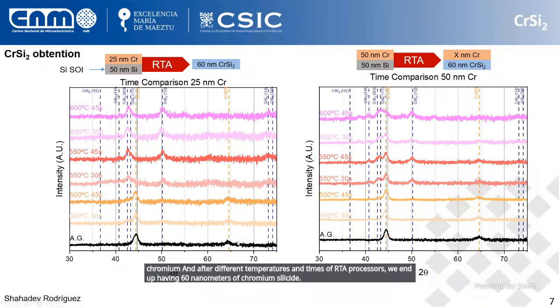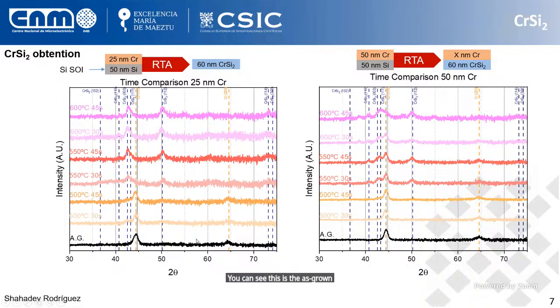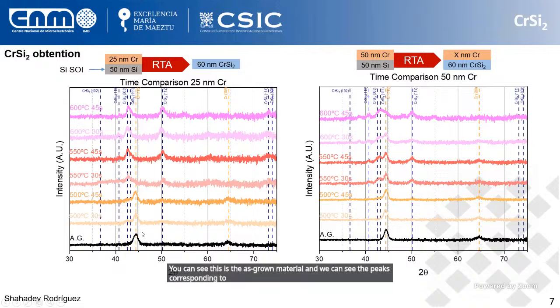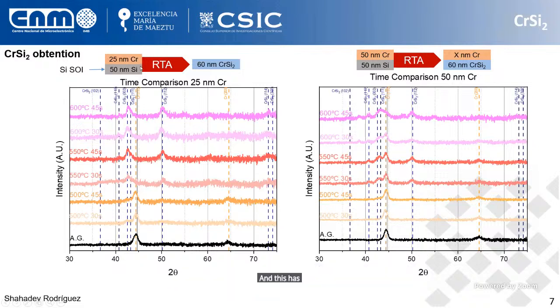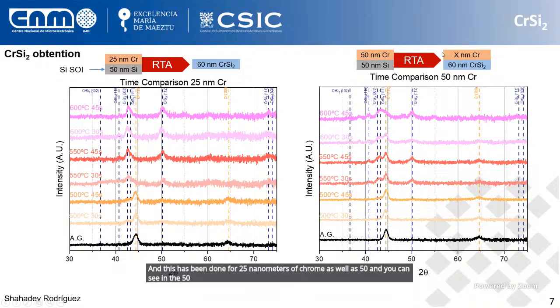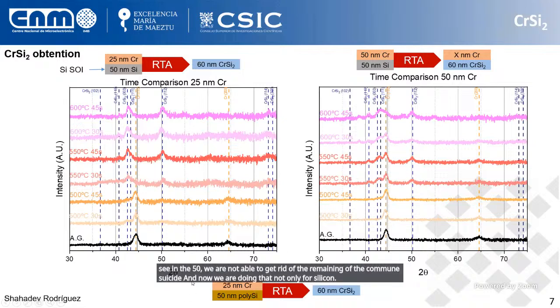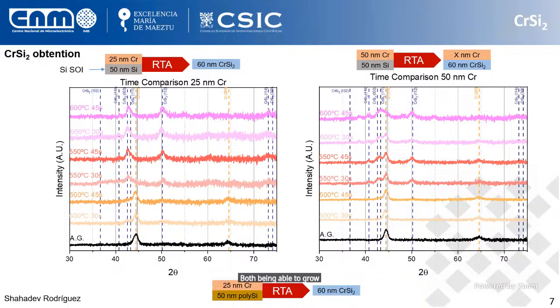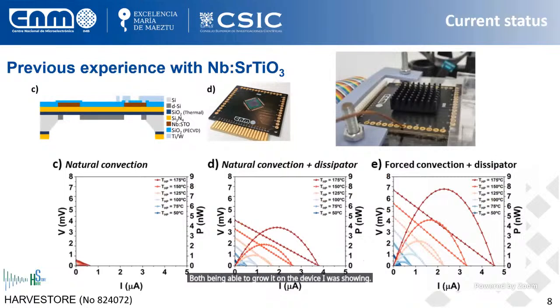You can see this is the as-grown material, where you can see the peaks corresponding to chromium. And as you increase the temperature over time, they start disappearing, and we start seeing the peaks corresponding to chromium silicide. And this has been done for 25 nanometers of chrome as well as 50, and you can see in the 50 we are not able to get rid of the remaining chromium. And now we are doing that not only for crystalline silicon, but also for polysilicon, to be able to grow it on the device I was showing before.